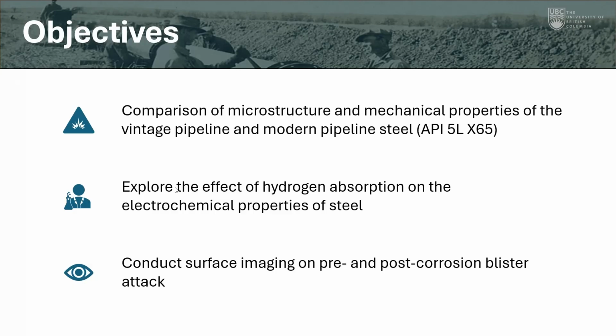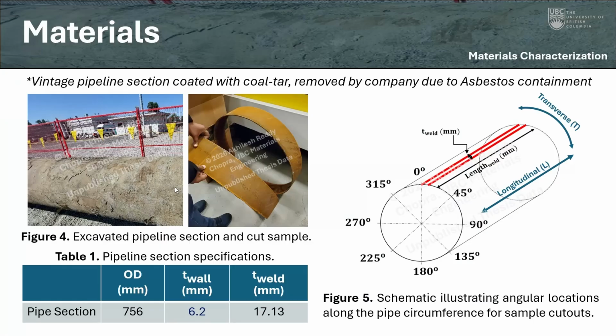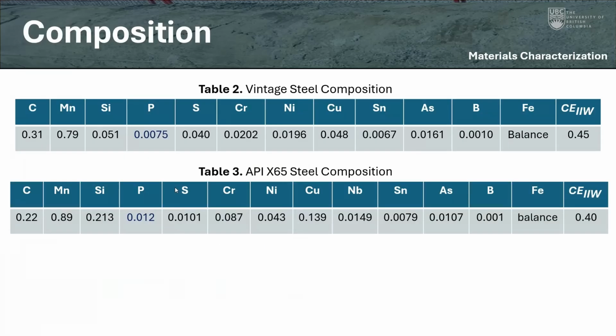And then finally, I have some images on both pre and post corrosion blister attack. So this was a few images of the pipe that we received from a company that I cannot name. And we extracted tensile dog bone samples and coupons for the test from various locations along the circumference of the pipe, 0 degrees referring to the weld line and 180 referring to furthest from the weld. And we also extracted samples along the weld line as well as transverse to the weld line to assess any potential anisotropy.